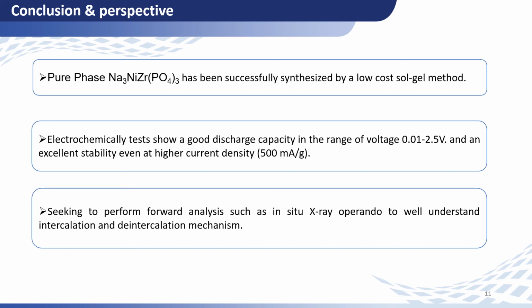Electrochemical tests show good discharge capacity and an excellent stability at a high current density. As a perspective, we are seeking to perform further analysis, such as in situ X-ray operando, to better understand the intercalation and deintercalation mechanisms of our phosphate-based material.